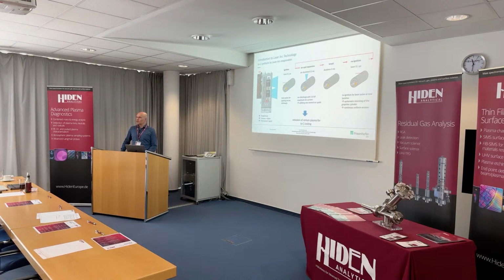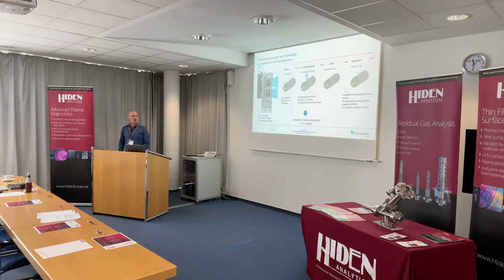For the ignition, it's a short pulse laser, 100 nanoseconds, to generate some initial plasma. And then we start an arc discharge with a high current. In this case here, 1.6 kiloamps is a usual number we are using. And then we have some spot splitting, as is also described a lot in the literature. It's more difficult on carbon because we don't have a fast movement of the cathode spots on the surface of the graphite. So we have to stop this process after some milliseconds or some microseconds in this case, wait a little, so there is some time in between, and then we reignite it at a different position. And if we scan very fast, we have a linear carbon source after all.